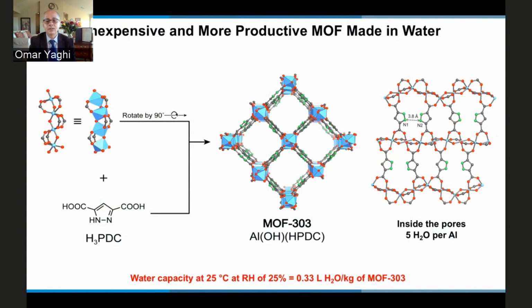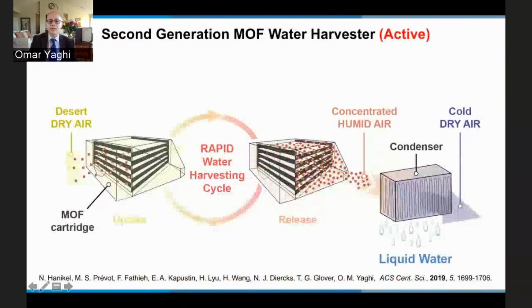But the beautiful thing about reticular chemistry is that the MOF was a zirconium MOF, and zirconium is expensive. So you can go back and design a MOF, in this case, a rod SBU MOF from aluminum, using this linker to make this structure we call MOF 303, made from rods that are arranged in parallel and linked by this organic linker. And this MOF works even better than the zirconium MOF. I want to point out that if you're a molecule floating in the channels of this MOF, you'll see that the nitrogens of your linker are pointing towards each other to make what later you'll see is a hydrophilic pocket. And the next pocket is a hydrophobic pocket. So you have alternation of hydrophilic, hydrophobic, hydrophilic, hydrophobic throughout the structure. And so we took that MOF, and now we use thin films in cartridges.